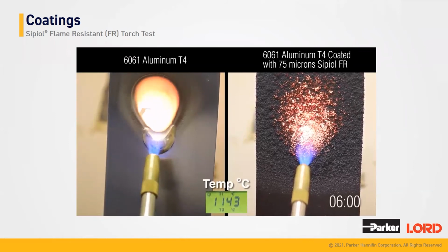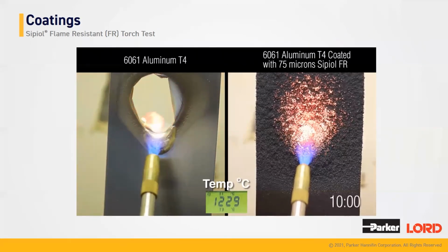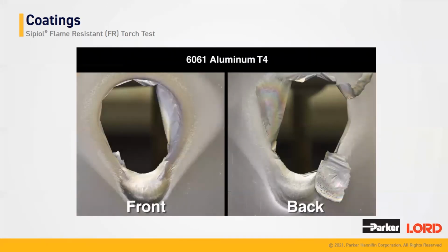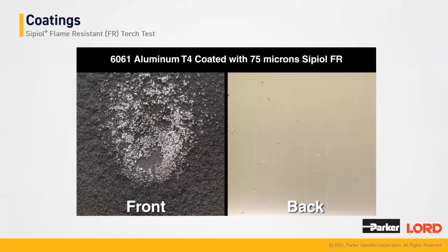We saw in our tests that coatings as thin as 25 to 50 microns are sufficient to protect aluminum. For substrates with lower melting points, thicker coating applications are used. And one thing I can add, Dennis, is that it not only protects from fire, but it also helps to keep the temperature down at the backside of the panel, which may be very useful as well. Absolutely right, Christoph. Thank you very much.